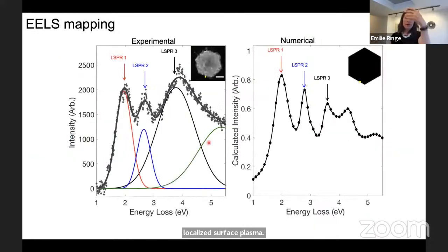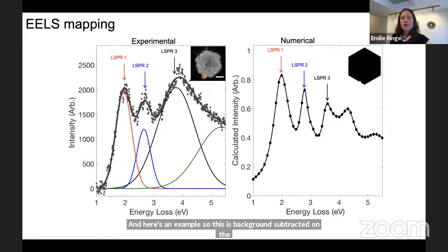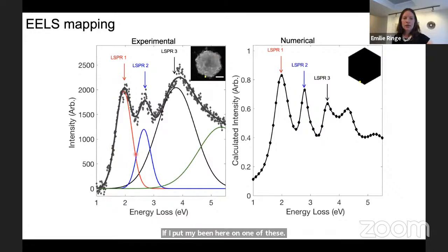Here's an example. This is background subtracted on the left - if I put my beam here on one of these hexagonal nanoparticles, I see a number of bumps. I can fit these bumps to different peaks, and then extract a map. We can also do numerical modeling - this is EDDA, solving Maxwell's equations but for an incident electron beam. The response matches really well because we use the correct amount of oxide on the substrate, and so on and so forth.